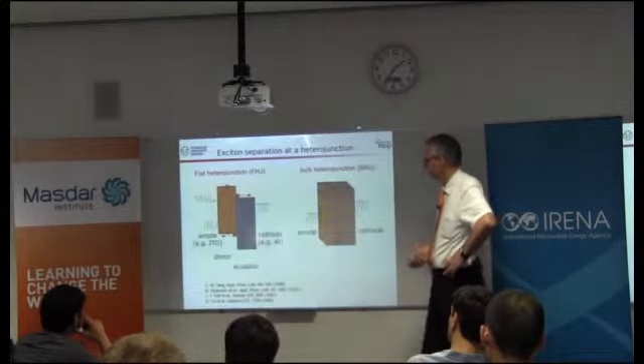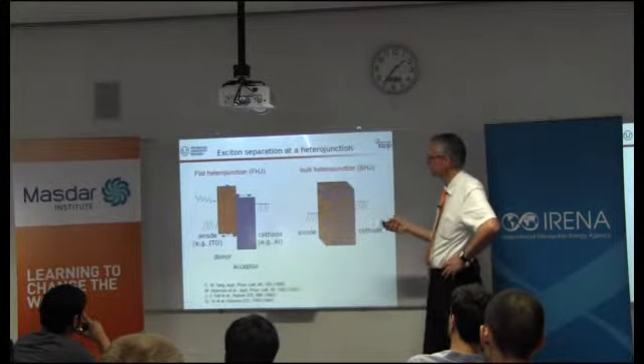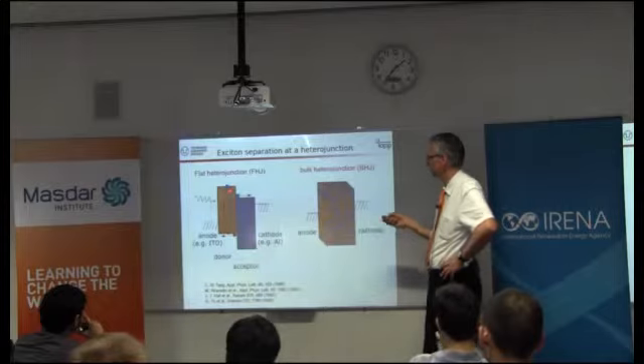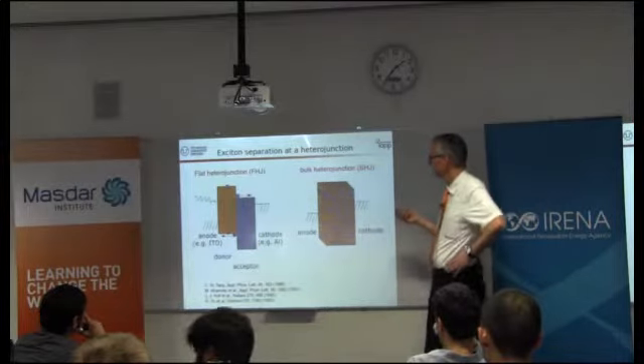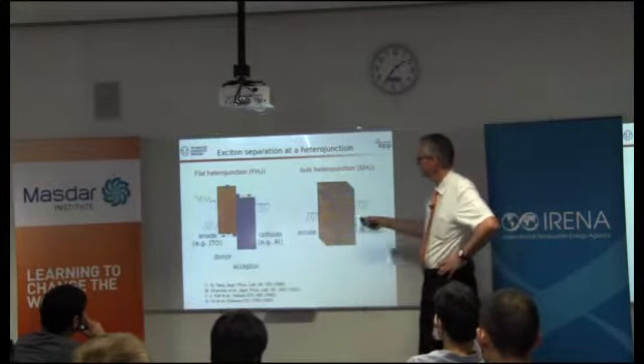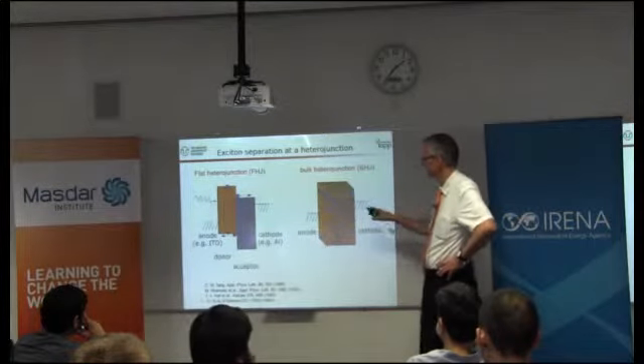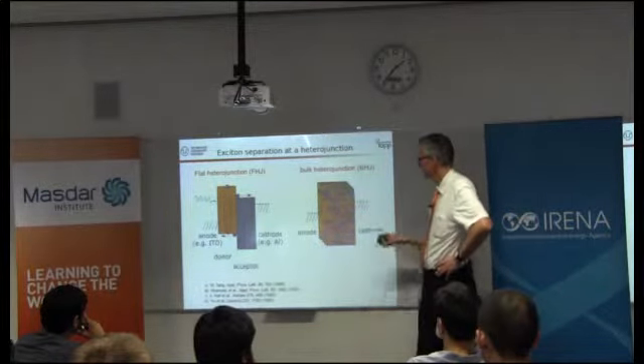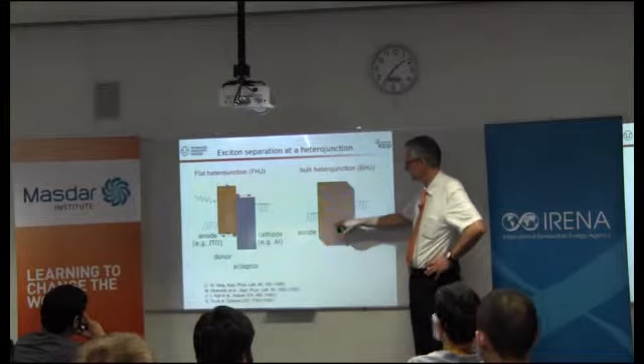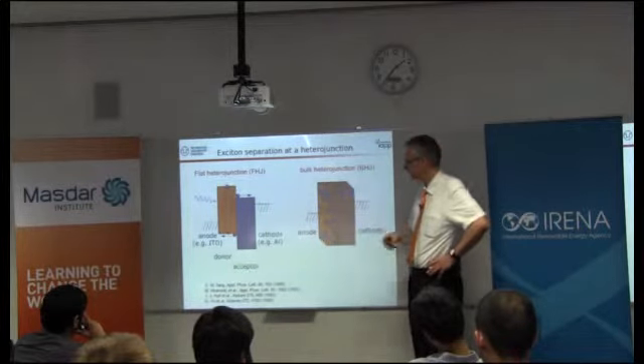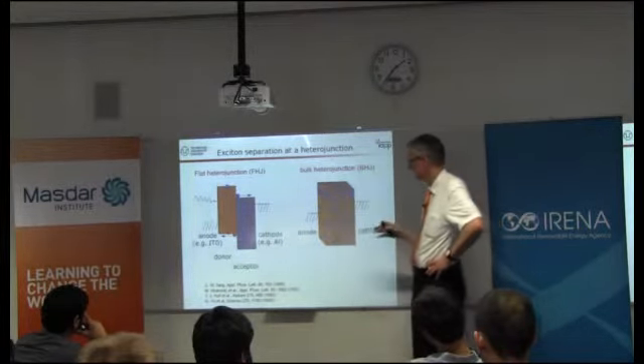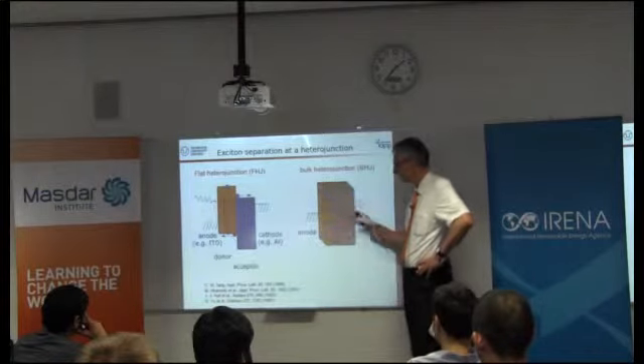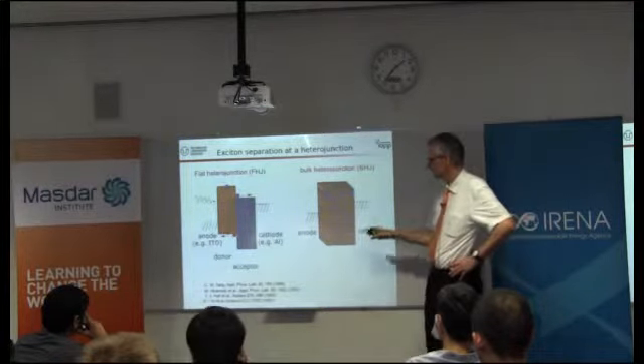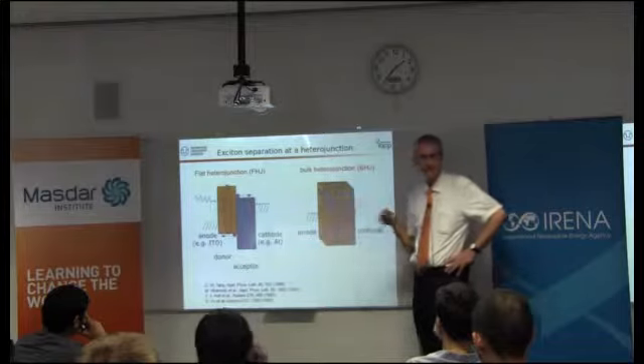And as said, the way to separate is a heterojunction, and to combine with the short diffusion length, the ideal solution is the so-called bulk heterojunction, where you mix the two materials. And typically these domains should be on the order of 10 nanometers or less. And that is actually very difficult, first of all, to achieve this morphology. Secondly, to characterize it and control it.